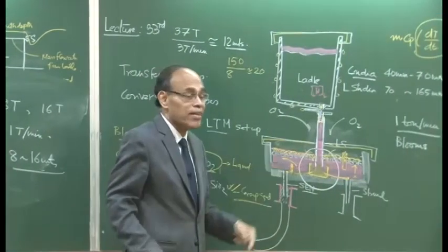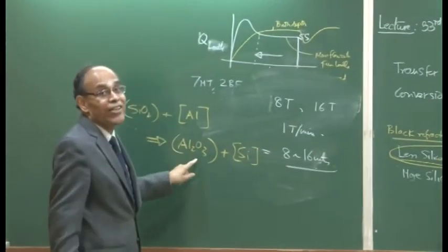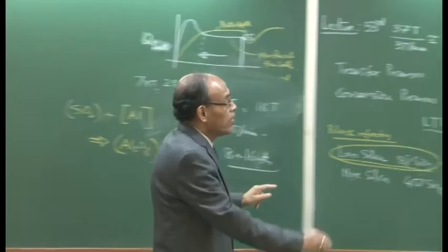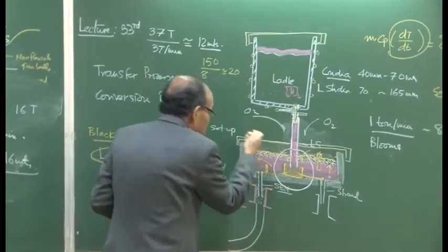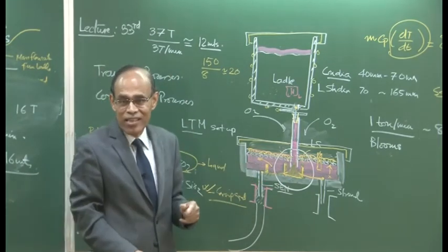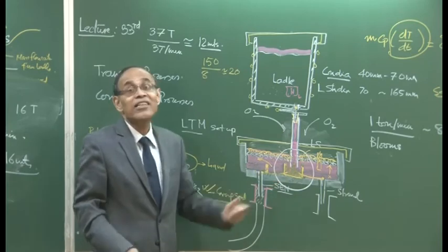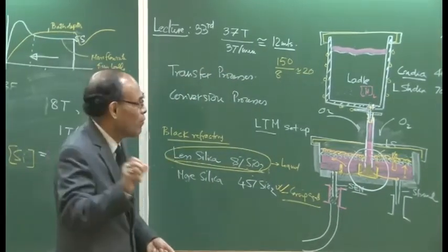will get contaminated. This is called reoxidation via the top layer, and if tundish has oxygen already present, tundish is not flushed, it is not covered, then we will call it atmospheric air reoxidation in tundish. So, reoxidation in tundish is a very big challenge. We must understand that we have spent so much effort.